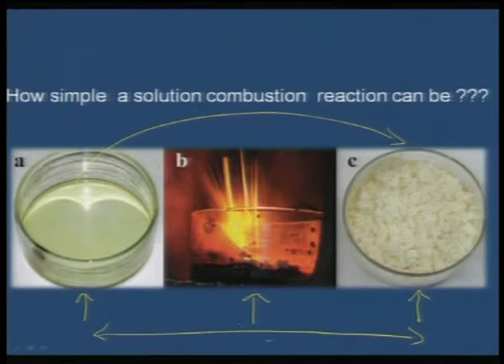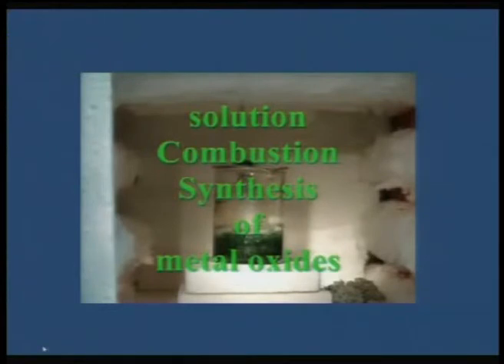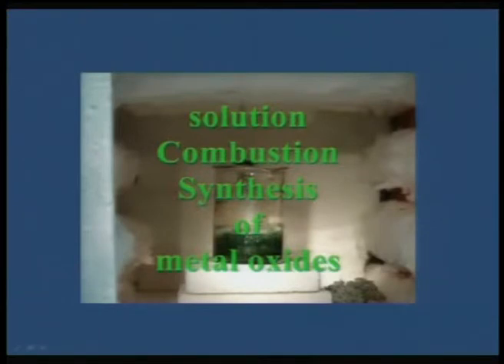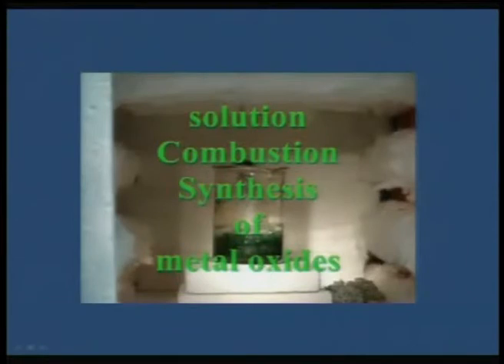From the time you make the solution to getting the product after inserting through a furnace, the whole process takes less than 2 minutes. The furnace — an open muffle furnace — is maintained at 500°C. Instead of a petri dish, you can use a 250 or 500 ml beaker, put the solution inside the preheated furnace, and observe the reaction happening.